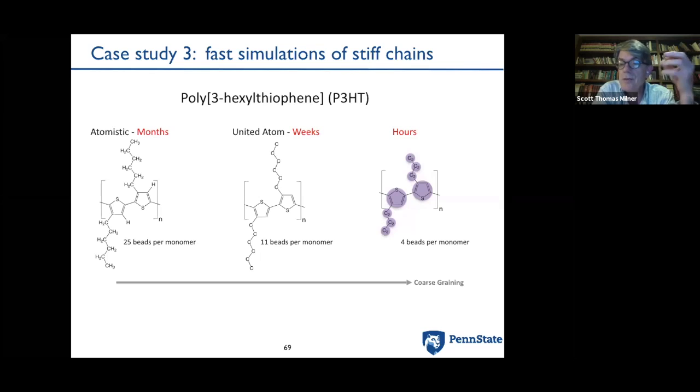So as soon as you replace those rings with one moiety, it's a round moiety, and then your molecule doesn't know anymore, so to speak, that it's made of planar objects, and so it screws up the packing. It doesn't pack the way it would pack if it were really planar thiophene rings, which are quite thin compared to the other dimensions.